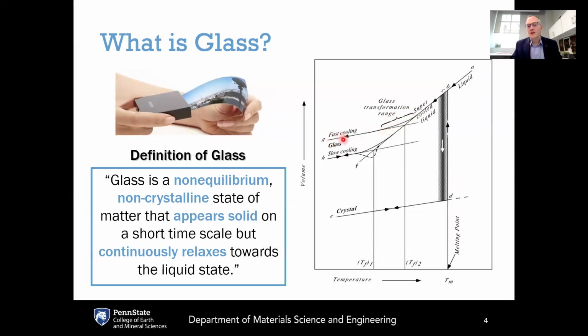And then the structure of this fast cooled glass reflects the structure of the supercooled liquid at a higher temperature. On the other hand, if you cool the supercooled liquid more slowly, you're giving the system more time to stay in its metastable equilibrium and only become kinetically frozen at a lower range of temperatures. Therefore, it would undergo the glass transition at lower temperatures, and then the frozen in structure of the slowly cooled glass would reflect that of a lower temperature supercooled liquid, whereas the structure of the fast cooled glass would reflect that of a higher temperature supercooled liquid.